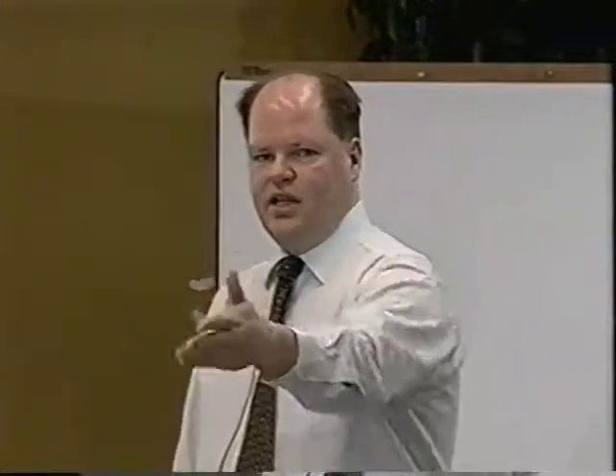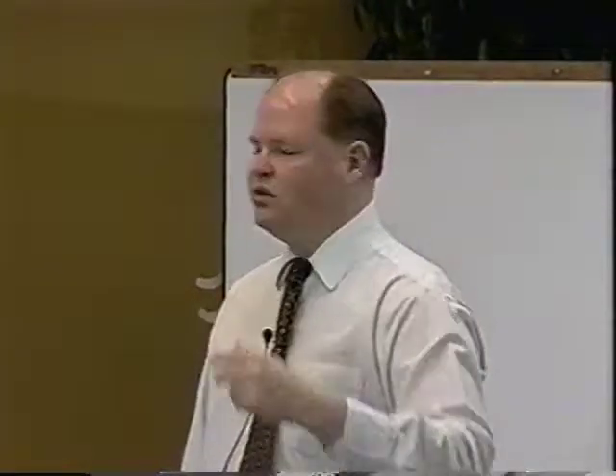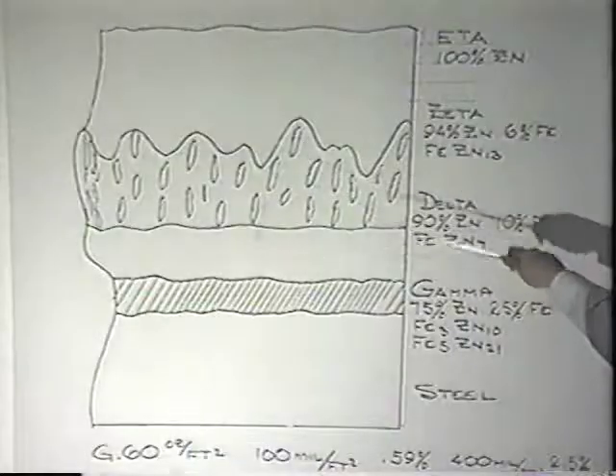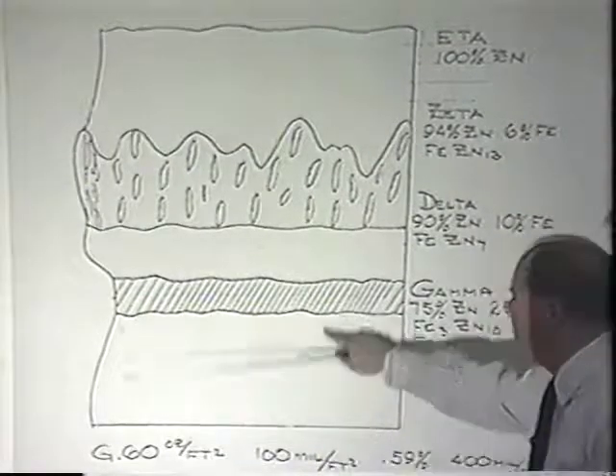We actually have to rough it up at the temper mill on the hot dip line in order to give you something for paint to stick to. Otherwise, it'd be too smooth to paint. I mean, it looks like a mirror. So that's how we got away from the spangled coatings that most people are familiar with. And that's what most people do on a hot dip line nowadays anyway, unless they're producing specifically for trade that wants a spangled product. A lot of the newer lines coming on are spangle-free lines.